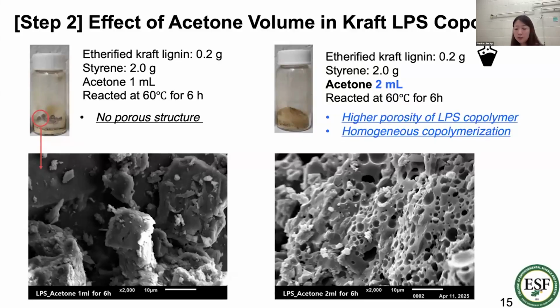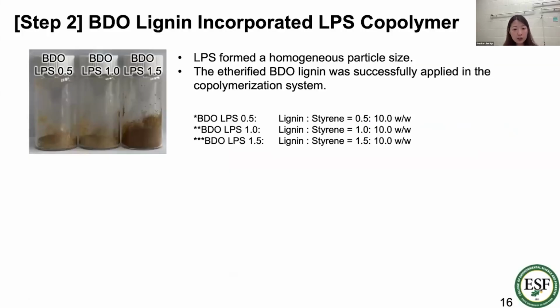And we observed better porosity of LPS copolymer once we increase the volume of solvent for the lignin dissolution. This result indicates that the homogeneous copolymerization was successfully conducted with the higher volume of lignin solvent. So we used Kraft lignin to set up this polymerization system, and we applied BDO lignin in this polymerization. All LPS copolymer showed even size distribution, and we successfully applied the modified lignin around 15% in the copolymer structure.